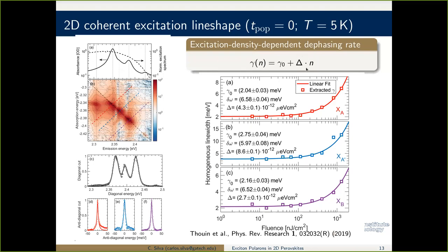And there will be a dependence of the dephasing on the density. So if I measure the dephasing through the homogeneous line width, I measure the dephasing as a function of density. Well, here it's plotted as a function of fluence. We see that there is this linear dependence. It's this linear log. That's why it looks like this, but it is linear, that we can then pull out these parameters. And it turns out that if you do that for exciton A, look at what the intrinsic dephasing is. Well, it's measurably different, but it's same ballpark, but it is measurably different.